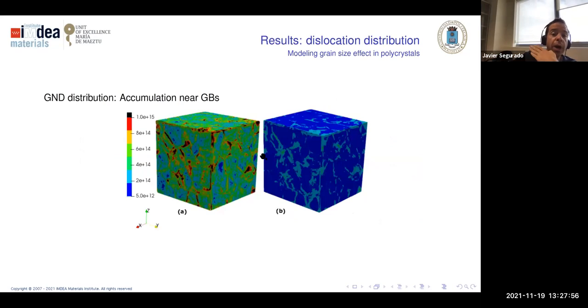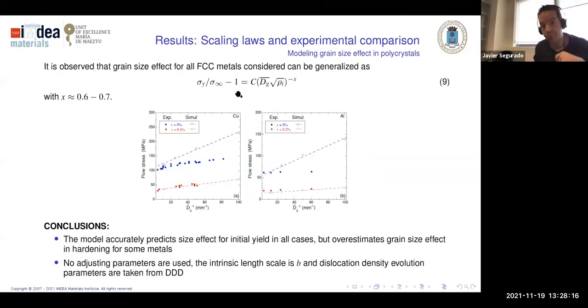Where do the GNDs appear? Where we have this curl of Fp. Mainly near the grain boundaries, where we have plastic incompatibility. One grain wants to deform in one direction and the other in another direction, and then these GNDs appear to make this compatible. And what type of equation can we fit? It is a bit more complex than Hall-Petch. Hall-Petch is very old, so everybody knows that this is the correct scaling. We find equations with an exponent that is not 0.5, it is a bit bigger, and a scaling that depends on the grain size, but also on the square root of the initial dislocation density.